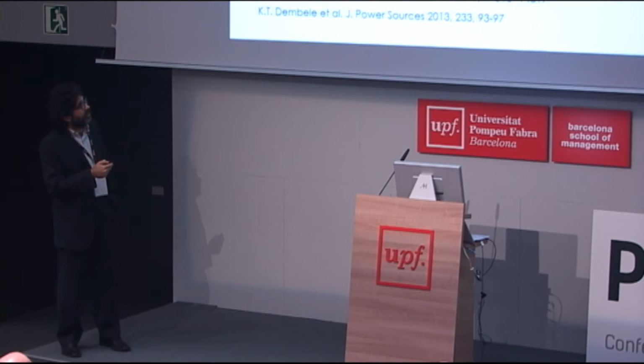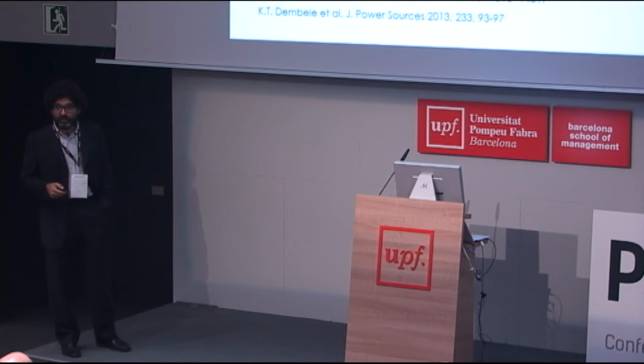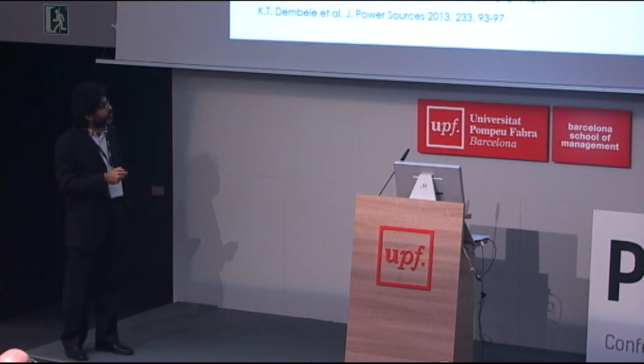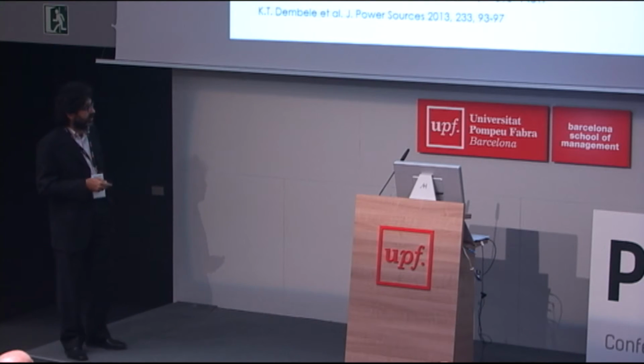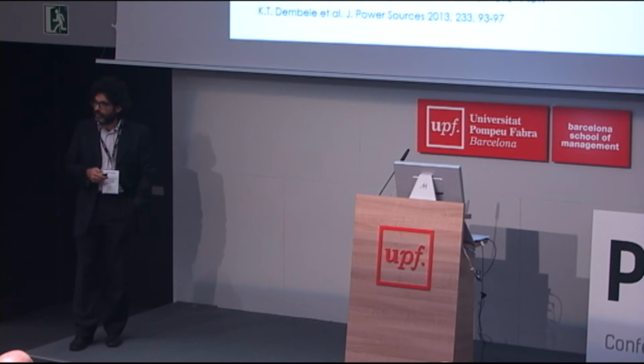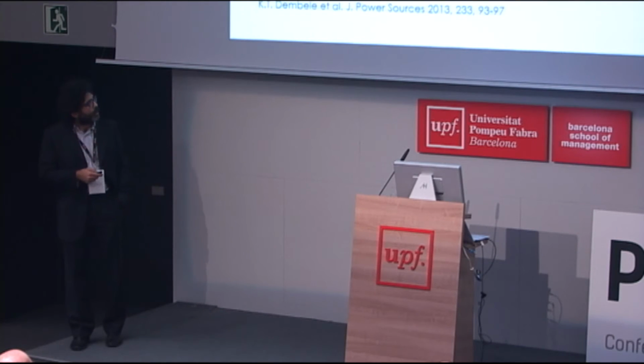You can see that by using this small concentration of carbon nanotubes, we were able to go from 6.5 to 8.1 photoconversion efficiency, and in the optimized system from 7 to 9%, which was pretty good for us, this kind of increase in these cells.